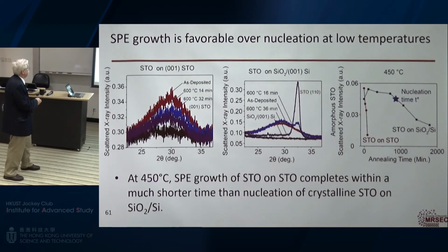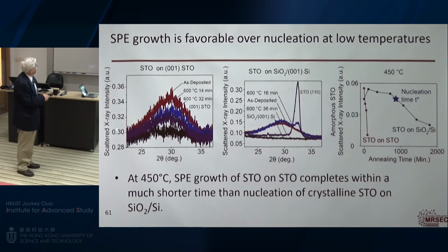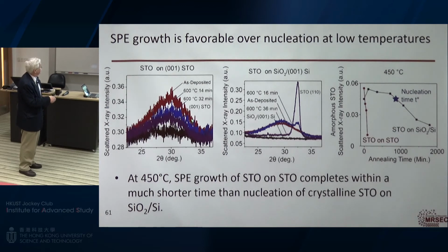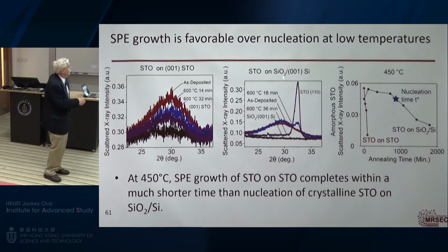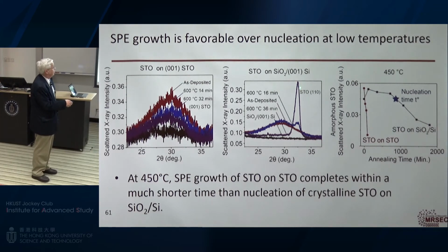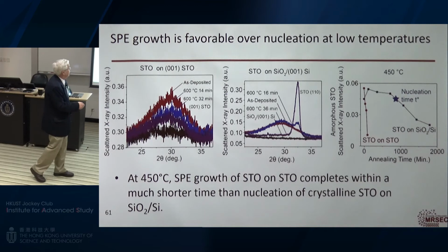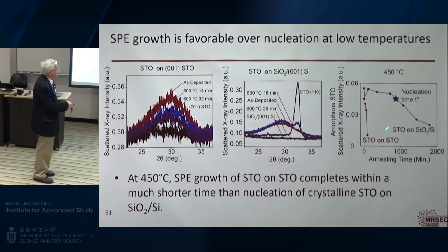Now we can do that. We studied this in great detail using strontium titanate on single crystal strontium titanate. And so I'll walk you through this, and it basically says that if I deposit amorphous strontium titanate on a single crystal and heat it up, eventually this amorphous peak goes away because it becomes crystalline. If I do this on SiO2, so there's no epitaxial seed, it becomes polycrystalline eventually. But the rate at which this amorphous peak goes away, or the rate of crystallization, is very different whether it's on an epitaxial or seeded substrate or whether it's on an amorphous substrate, where it has to have homogeneous nucleation.